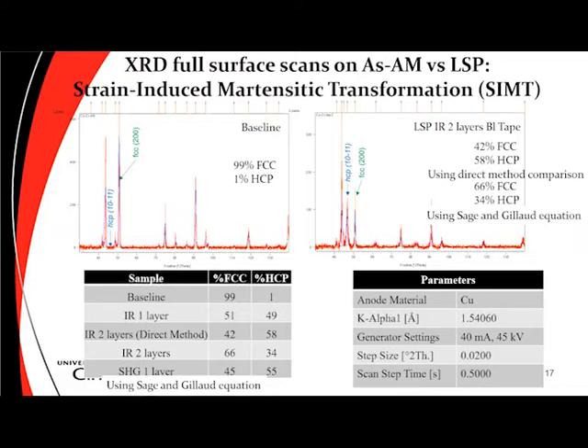Usually, this is very detrimental to cobalt-chromium alloys during cold work because crack nucleation and propagation starts along the HCP phases. However, strain-induced martensitic transformation is very beneficial as it significantly increases the strength and wear resistance. Hence, controlling this particular phenomenon is very relevant in the development of more durable alloys.